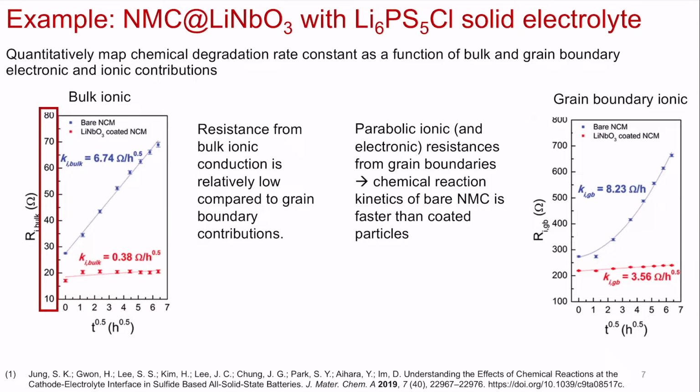But if you produce, let's say, upon charge, the oxidative decomposition products, the various oxides that we mentioned, if they're passivating, like Li2O, then those will stay, and they're most likely not going to induce any more reaction, and thus the linearity is not anticipated to continue.